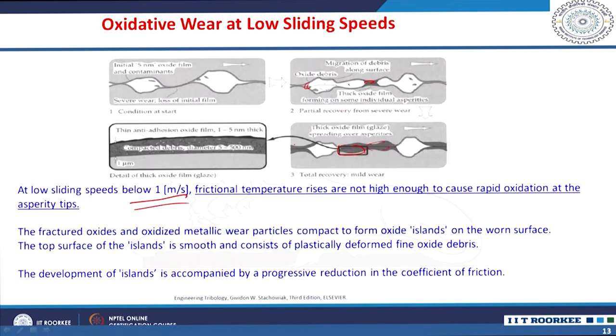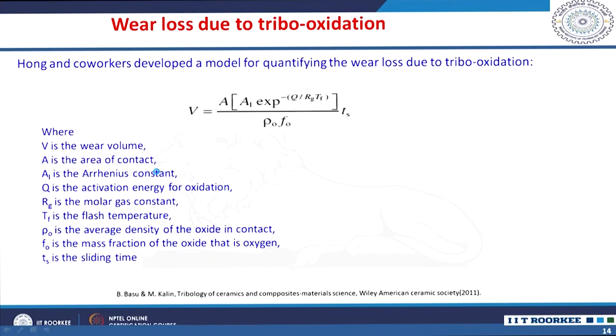The top surface of these islands is smooth and consists of plastically deformed fine oxide debris. So, development of such islands is accompanied by progressive reduction in the friction coefficient. So, you will have a compacted debris forming a layer which is plastically deformed. Development of such islands is accompanied by the progressive reduction in the friction coefficient at low sliding speeds.